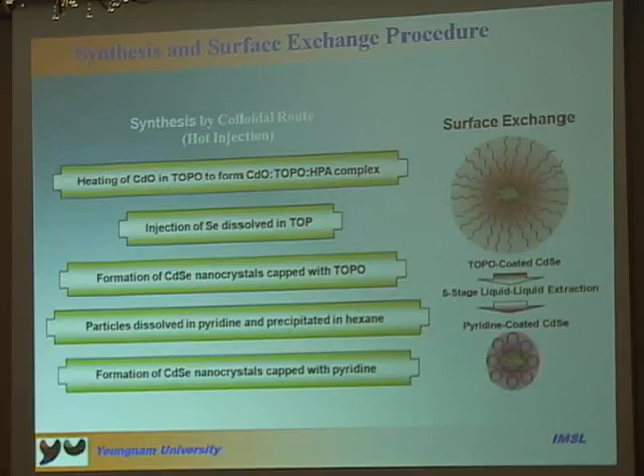Now, let me talk about the synthesis of cadmium selenide by the colloidal route. We use the hot injection method. After we follow this process, we have cadmium selenide nanocrystals with TOPO, but we don't want to use TOPO coated CdSe because TOPO has a very high boiling temperature. That's why we change from TOPO coated to pyridine coated CdSe.